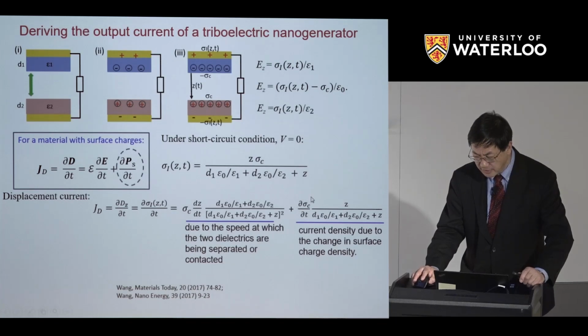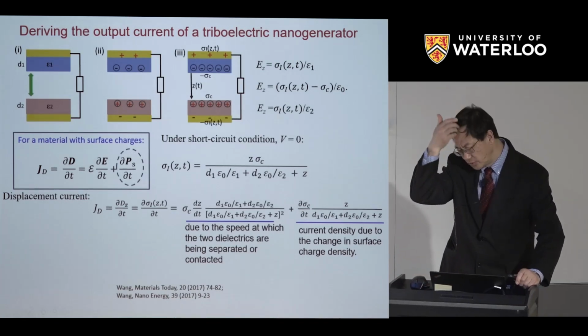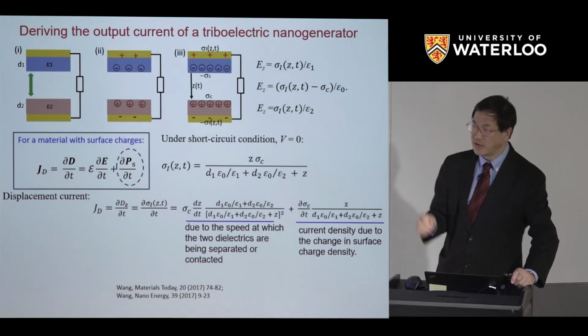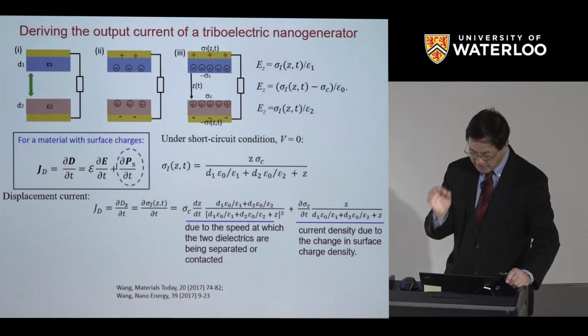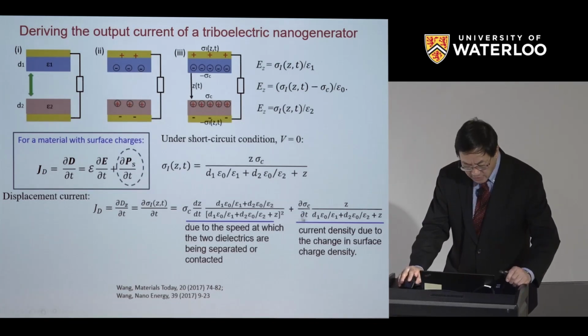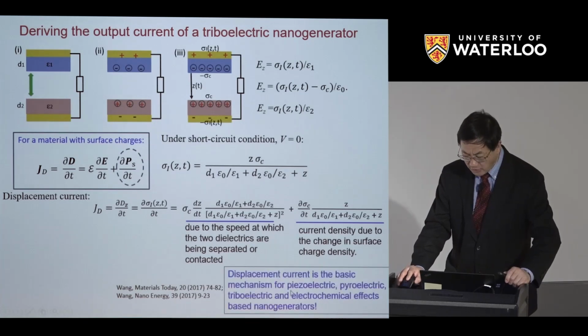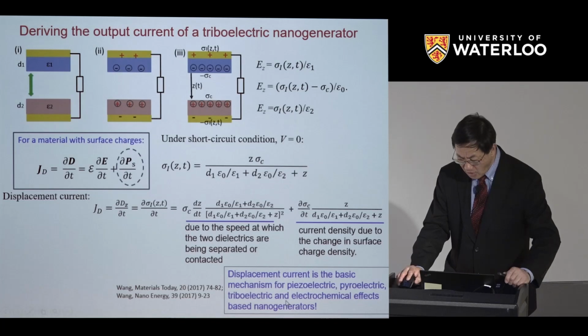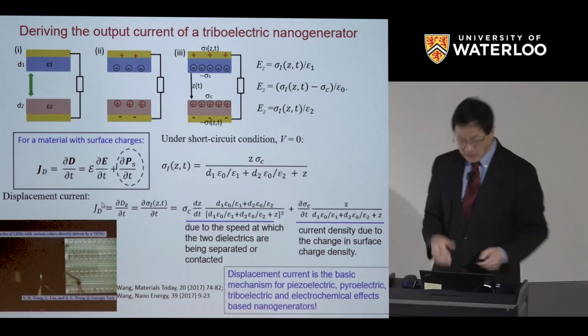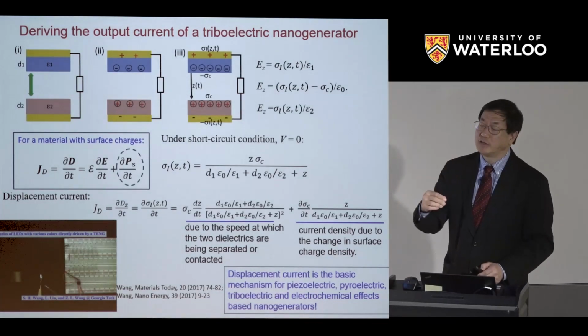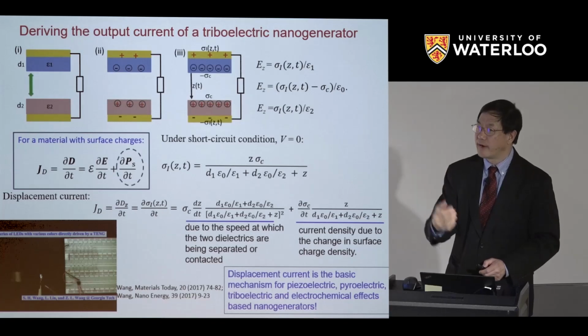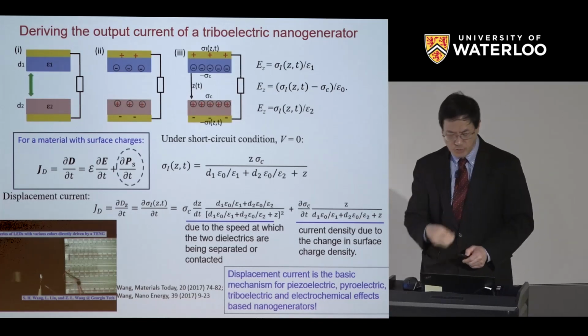And I think Professor Joe's student showed me this morning that they have a titanium oxide, and using a breath on it can generate current, which is due to the change of this electrostatic charge density here. Our triboelectric generator is mainly due to the first term, because the other is a constant, so it is the speed at which. So this is unified: piezoelectric effect, pyroelectric effect, or triboelectric effect, as well as electrochemical effect for power generation. All of it goes to displacement current here. So this is our understanding of how the displacement current, used in the electromagnetic field, now comes to the energy field we are interested in.